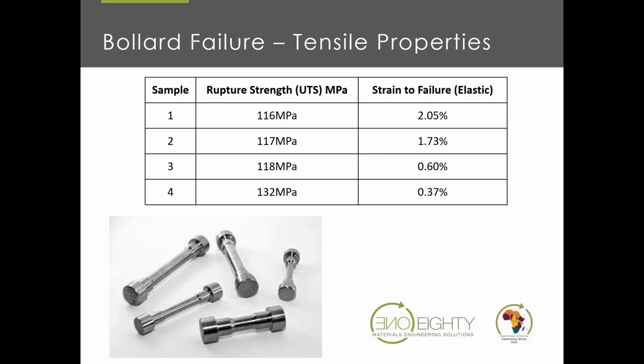So a stainless steel, for example, will elongate by 20% before it fails. Aluminium, up to 40% before it fails. Normal carbon steel, anything from 8 to 15% before it fails. So a piece of steel that can only elongate by 2% maximum, and in some cases 0.37%, means that there's absolutely no give in this material. It's not able to tolerate a load and absorb that load. Right. So that's a piece of information in the puzzle.